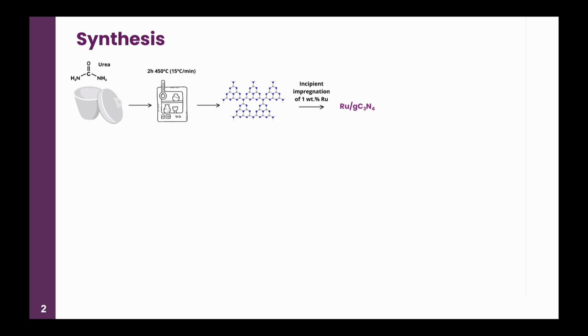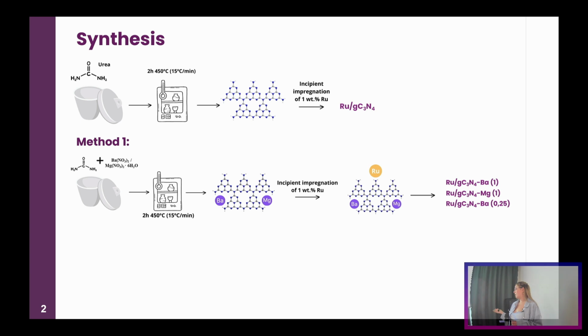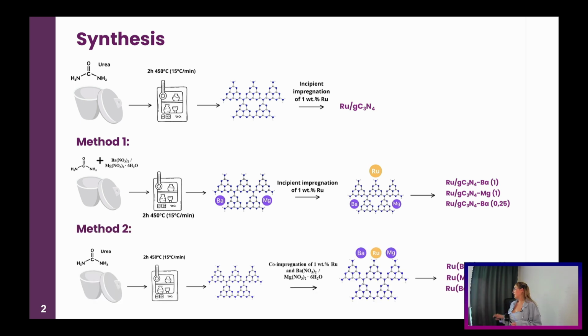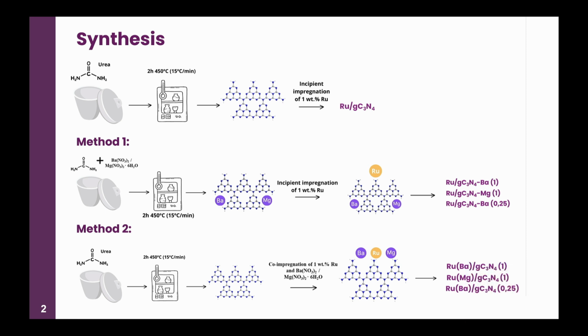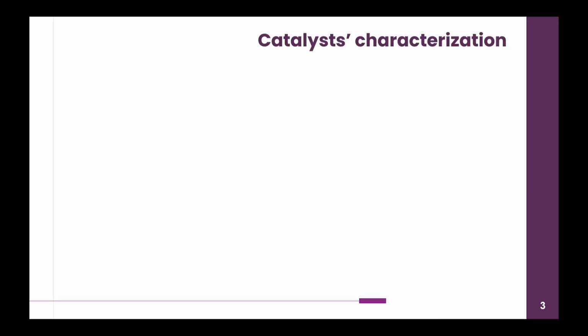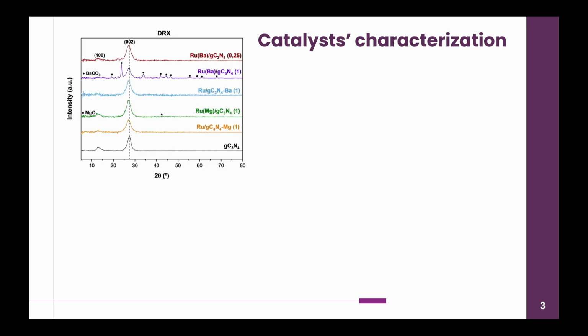Then doping with the alkali metal was carried out using two different methods. On the one hand, by mixing the alkali and the urea before the thermal polymerization, and on the other hand, by incorporating the alkali metal and the ruthenium at the same time by co-impregnation. We move on now to the characterization of the prepared catalysts. These are the X-ray diffractograms where we can see the two characteristic peaks of the C3N4. This peak is related to the interlayer stacking of the conjugated system, and this one is related to the in-plane structural packing of the s-triazine units.